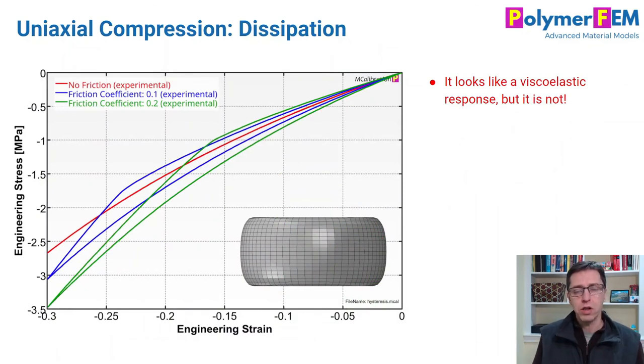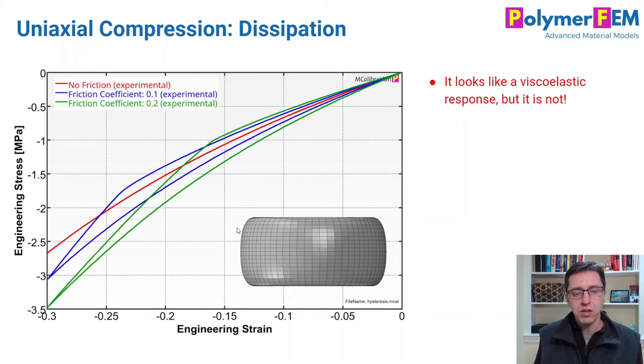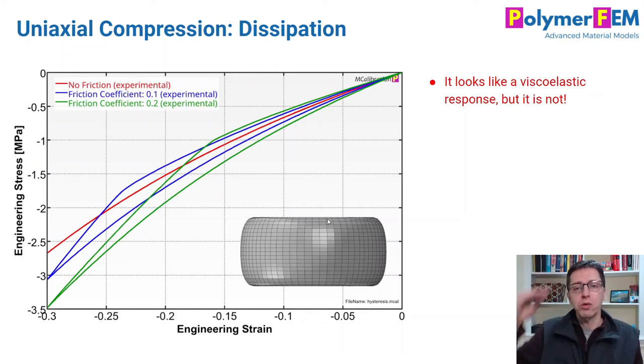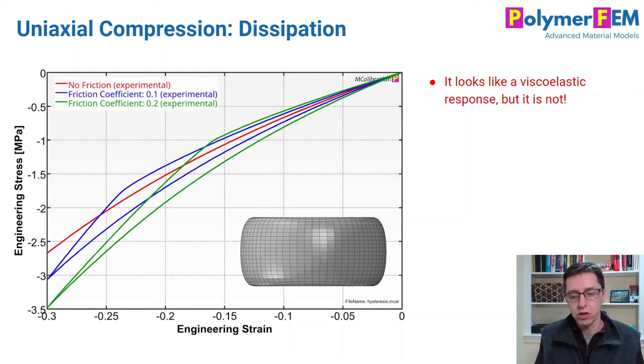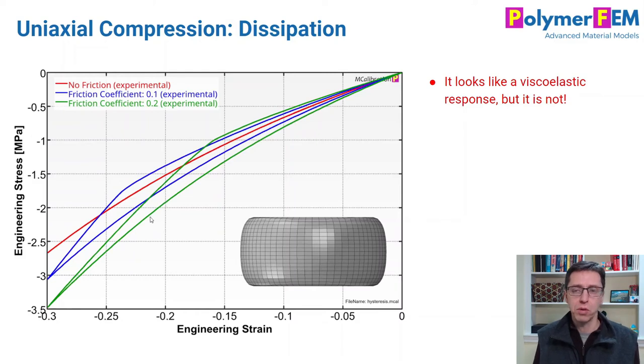Getting back to our initial question — can we get dissipative behavior, can we cause apparent viscoelasticity in a compression test? Let's take a look. We take a cylindrical specimen with a friction coefficient of 0.1 or 0.2 at the interfaces, compress it, and then also unload it. These are pure finite element simulations without any contact stabilization — it's a clean, simple contact. As we discussed, the higher the friction, the stiffer the response during the initial compressive phase.